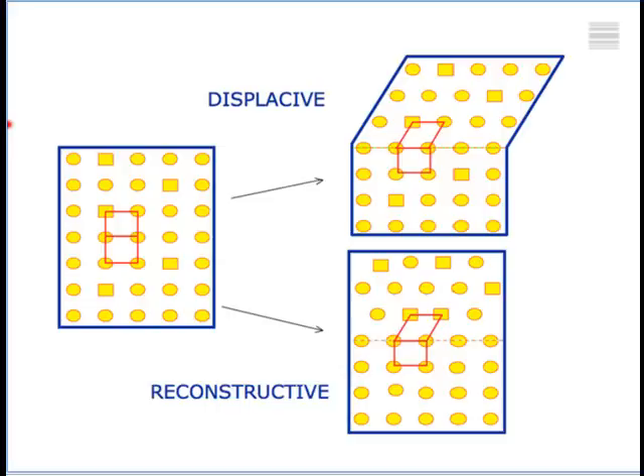The second way is, imagine that I break all the bonds between the atoms here and I rearrange them into a different pattern while maintaining the external shape here. So you can see the shape here is exactly the same as the shape here. For example, when water freezes into ice, it doesn't change the shape of the container. That's because in forming the crystals of ice, the molecules have moved to create a new pattern, so they can move while maintaining the external shape. And in that process of diffusion, some atoms prefer to be in the ferrite. So you can see that we have a lot more of the square atoms on this side than on this side. So this kind of transformation, which is, for example, pearlite or ferrite, can only happen at temperatures where atoms are mobile. And that typically means at temperatures in excess of about 600 degrees centigrade.